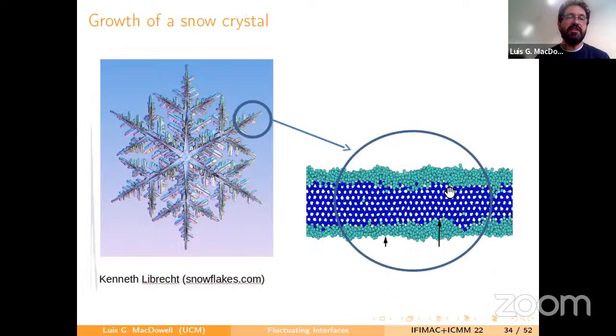In practice, I'm interested in studying crystal growth on snow crystals. And snow crystals actually are more complicated because if you make a close-up of the surface, what you're going to find is that, as I mentioned before, we have a pre-melting film. Ice and vapor phases are actually separated by a 1 nanometer thick sort of pre-melting film of water. So this interface is more complicated because it has to be described by two surfaces. One surface is bounding the pre-melting film from the bulk ice, and the other surface here is bounding the pre-melting film from the